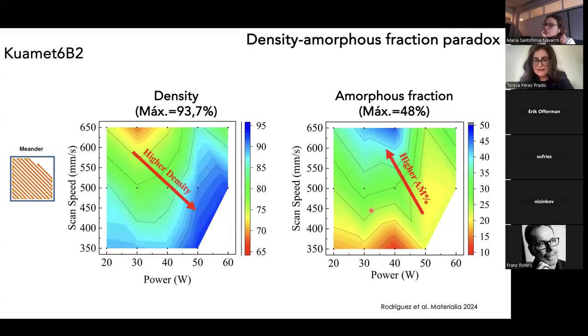And I'm putting here next to this graph what I showed you earlier regarding the density. Within the same processability window, this is the density map, and the arrow indicates the direction in which the density increases. So this is the second bad news here, because these are two variables we want to optimize simultaneously, the density and the amorphous fraction. But what we are seeing is that these two properties just vary in opposite ways with our processing parameters. So this is what we call the density amorphous fraction paradox. And it looks like using simple scanning strategies and these commercial alloys, it is not possible to overcome this paradox.